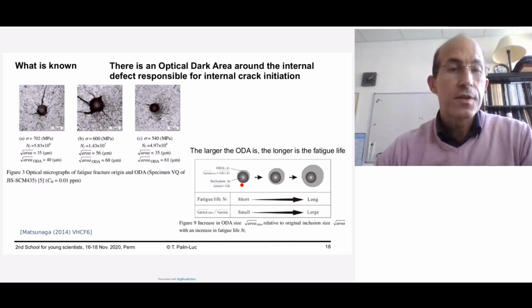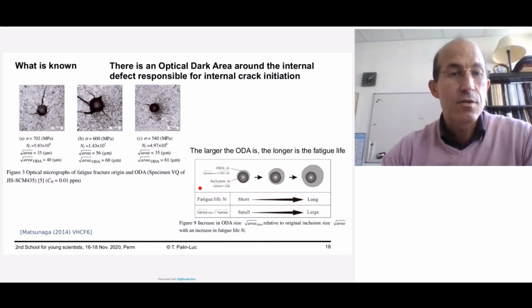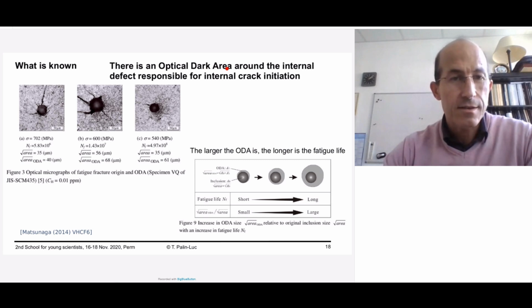When you have a look at the features on the fracture surface after a very long life, what you can see, if there is an inclusion, is the presence around the inclusion of an optical dark area around the internal defects. You can see this illustrated in these three pictures from Matsunaga during the 6th Very High Cycle Fatigue Conference in 2014. And you can see that if you decrease the stress level from 700 to 540 megapascal, the fatigue life increases from 5 million cycles to approximately 50 million cycles.